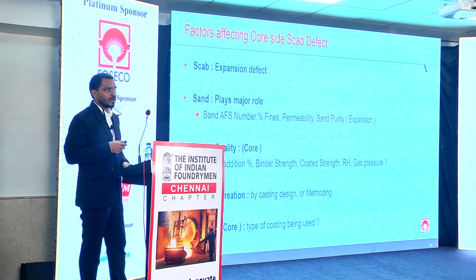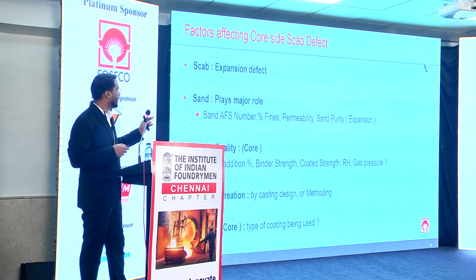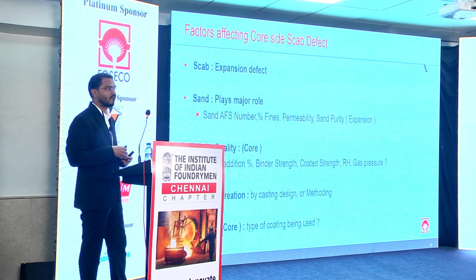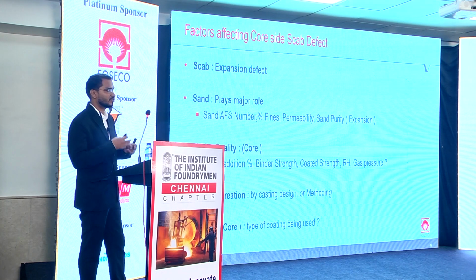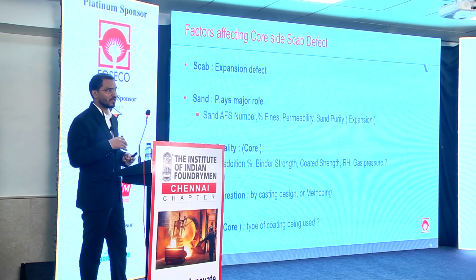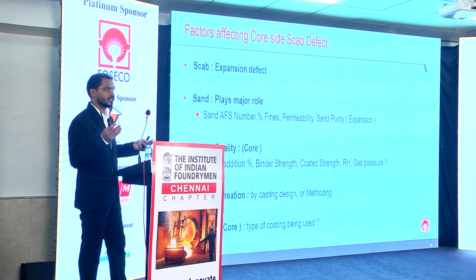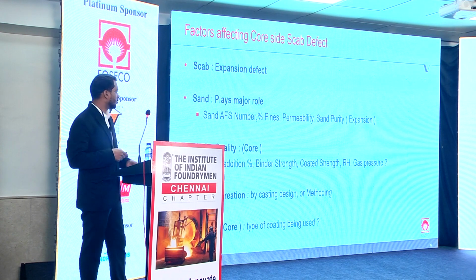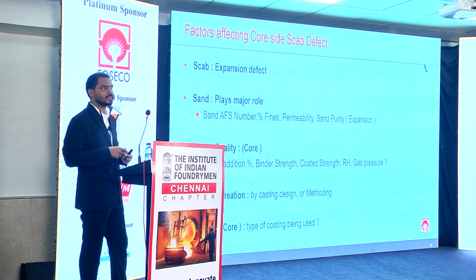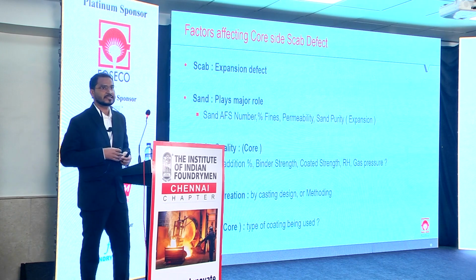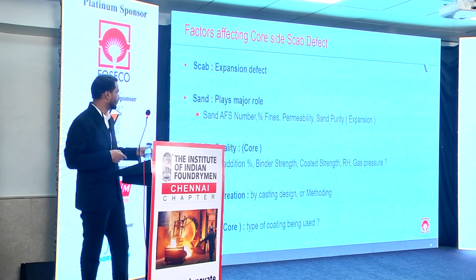So the major parameters, if you see, are playing major roles. This is sand: the type of sand, the AFS we are using, the distribution of the sand, and the percentage of fines. The more the fines, the higher the binder requirement, and the greater the tendency on bonding strength. Then lower permeability means a chance of gas pressure creation, and then again expansion, and then scab creation. If high quality sand is being used in the foundry, there is a tendency of more expansion, and there is also a chance of scab defects.